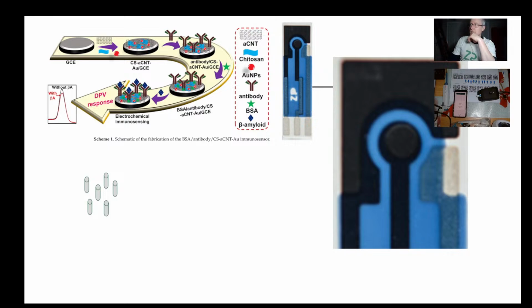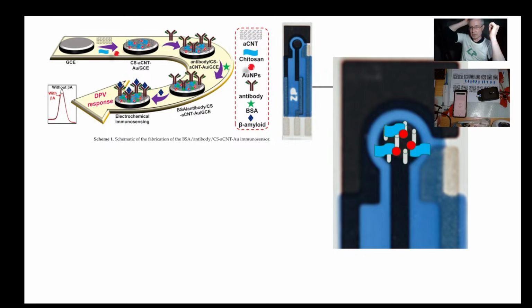Having read the paper, we've got these carbon nanotubes, we've got this chitosan, we've got these gold nanoparticles, and essentially these get deposited, in their particular case, onto a glassy carbon electrode. But as I say, you can't commercialize off a glassy carbon electrode. So in fact, what we would do is drop cast them onto a screen printed carbon electrode, and then the gold nanoparticles can basically be used to anchor the antibodies through a thiol atom or sulfur atom, and then they're blocking to stop non-specific binding using BSA, bovine serum albumin.